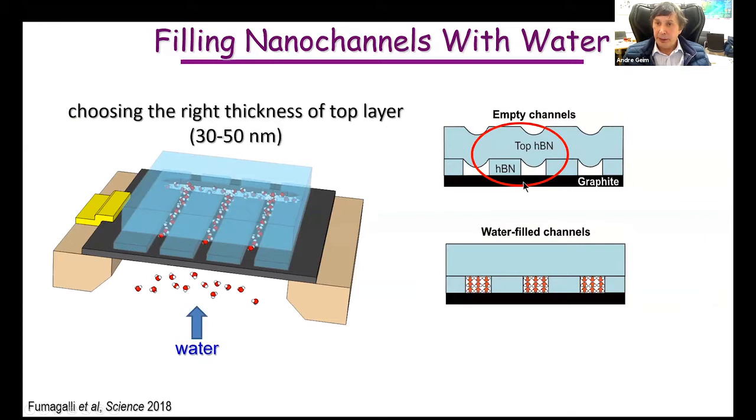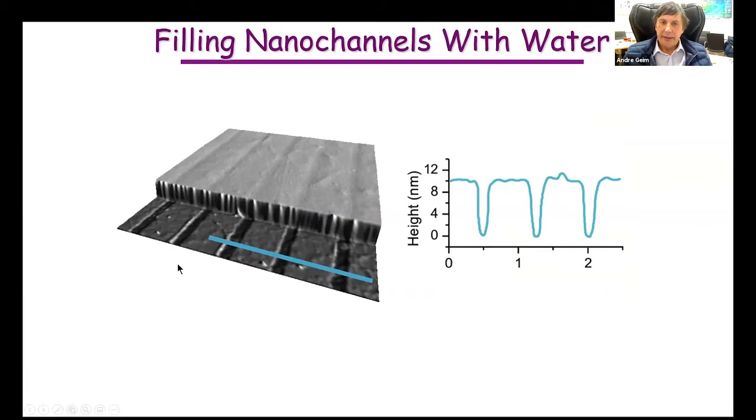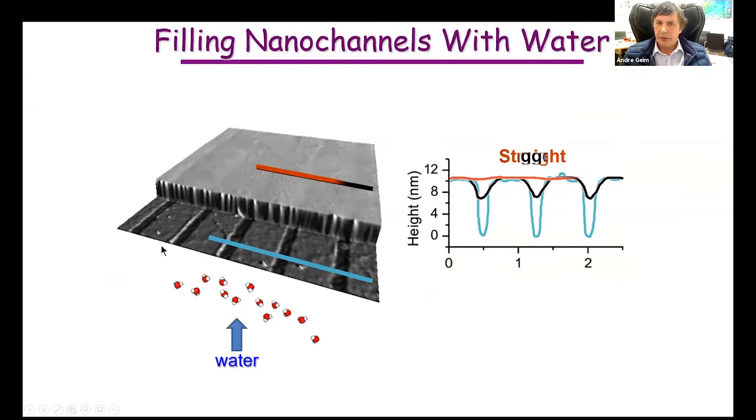And in this particular experiment, we use this assembly of graphite, which serves as an electrode. And everything else is essentially boron nitride, a low-K dielectric. So that's our channels in AFM, open part, and this is the top crystal. If we go on the top crystal, initially we see some sagging, which we design intentionally. We expose those channels to water and see that this sagging nearly disappears. You can sometimes still see a bit of sagging.